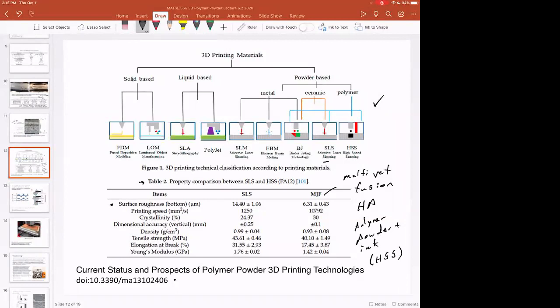And I think last time we talked about surface roughness, and it turns out that there's quantitative metrics for surface roughness and quantitative ways to measure surface roughness. And surface roughness really matters in metal SLS. So if you're familiar with powder bed fusion of metals, getting nice surface roughness is important because that creates mechanical stress concentrations in your part, and the surface of the metal has a big influence on the defects and crack propagation and how that metal fails. But surface finish is also important just for quality, for customer acceptance, for selling parts.